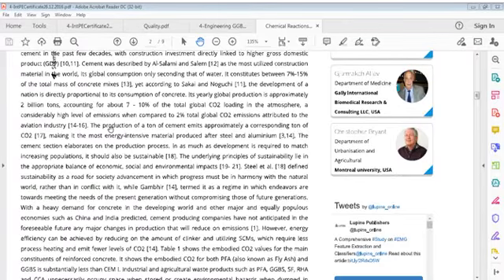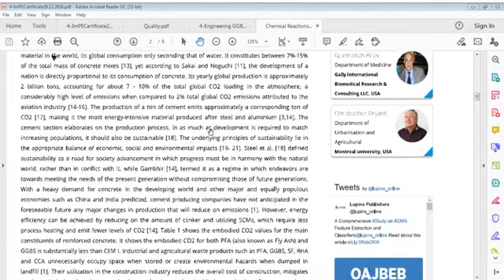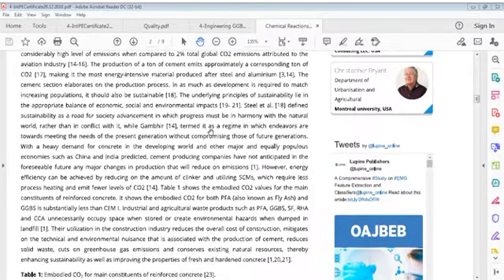Yearly global production accounts for about 7 to 10% of total global carbon dioxide loading in atmosphere, a considerably high level of emissions when compared to 2% total global carbon dioxide emissions attributed to aviation industry. Production of a ton of cement emits approximately a corresponding ton of carbon dioxide, making it most energy intensive material produced after steel and aluminium. The cement section elaborates on production process.